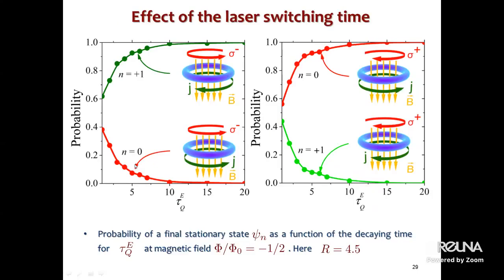Okay, here are the results. Here the probability of the final stationary state as a function of decay time is shown, the characteristic time of the decay. Clearly, the final superconducting state is determined by the helicity of radiation. Here it's counterclockwise, here clockwise. In the right panel we use one polarization, and in the left another polarization. We see almost 100% probability for slow switching times. When the switching time is fast, probability is rather small, but it approaches 100% for slow switching times.